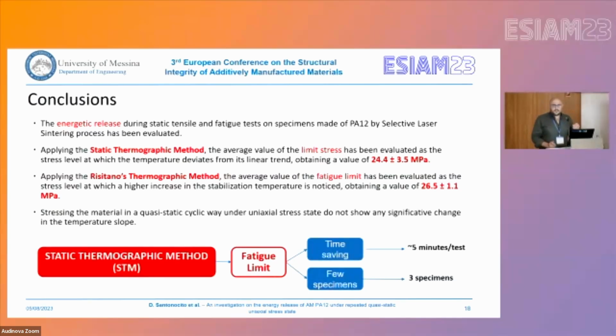I want to point out that to verify the obtained value of the fatigue limit stress that we have found, we have to perform a classical fatigue test campaign. On the other hand, this kind of campaign consumes a lot of time, and we also need a lot of specimens to be tested. For the static thermographic method, the test time is about 5 minutes, it is a simple static tensile test, and we just adopt one specimen. The same applies to the Risitano thermographic method.